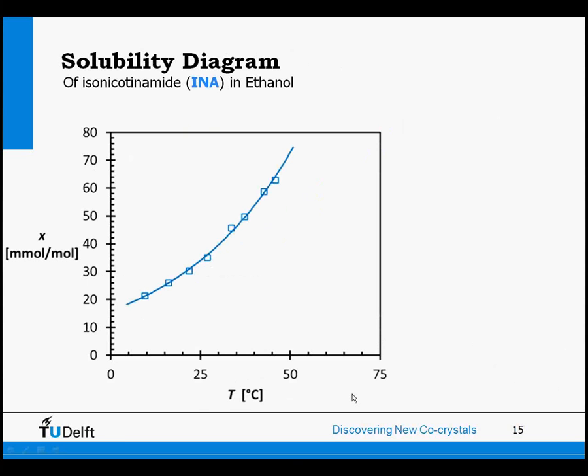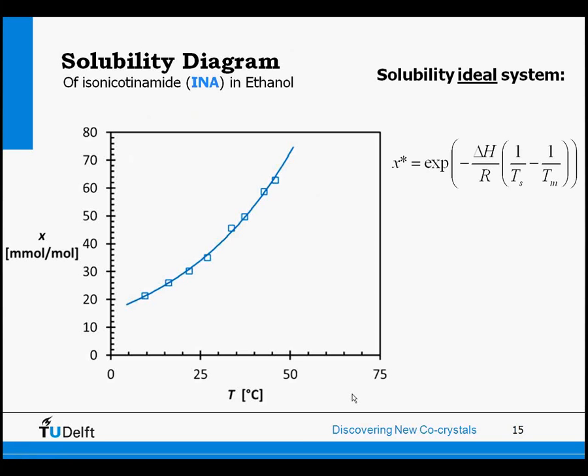And then you can measure the saturation temperature of specific compositions, and usually that is plotted as composition versus temperature. And then, for instance, for Isonicotinamide in ethanol, you get this diagram. And you see that solubility increases with temperature. You can describe these points with, for instance, the van 't Hoff equation, which is giving the solubility of an ideal system.